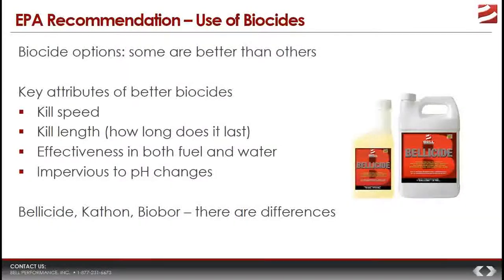First thing would be, how fast does it kill? What's the kill speed? That should be in hours, not days, of course. Second one is kill length. We typically consider this to be the most important one. It's the amount of time that a biocide will maintain 100% kill rate in the fuel. Now, how long should you look for? We're not talking about months here, we're talking about weeks. 4 weeks is about the best that you're going to get within the industry.